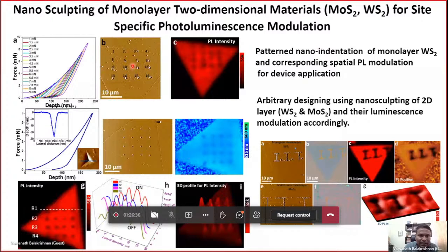If you look at the arrays, the first one is not even visible. This is for an incremental load. We have gone from a very small load of around 25 micronewton to a maximum load of around millinewtons. Of course, you can choose based on the substrate and how much you want to deform. The difficulty would be if you are doing it on a freestanding film. Doing nanoindentation on a freestanding sample would be very interesting, but we have not tried so far.